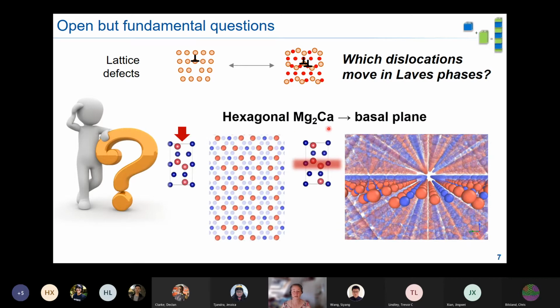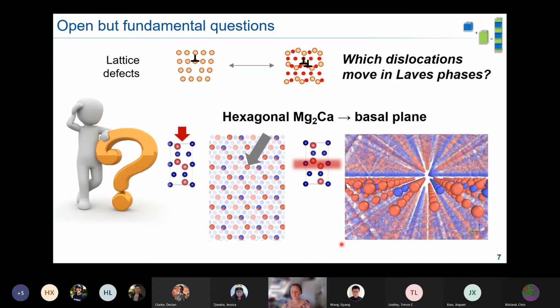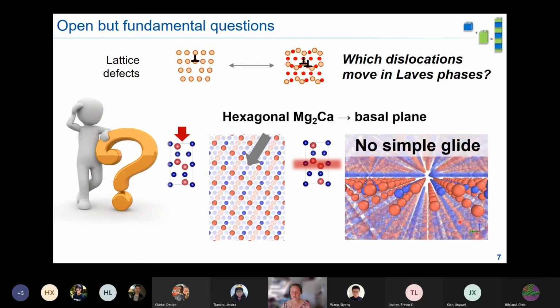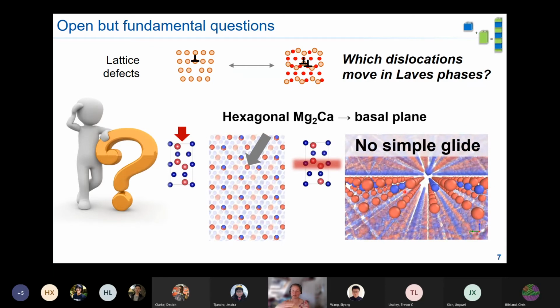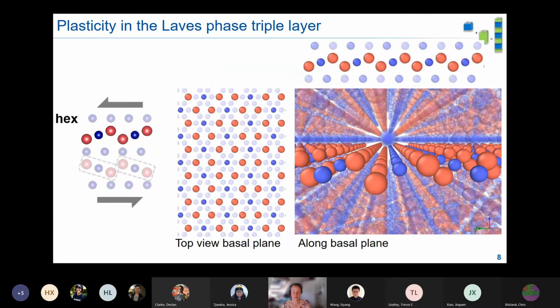There's one example, for example, hexagonal Laves phase, Mg2Ca. And if you look into the basal plane of this, and you can do some atomistic simulations, because for this we actually have potentials, then we can, of course, look along the plane, and we can look from the top, and we then try to shear the crystal lattice. It actually looks all right, right? You think, yeah, you shear like this, and then you get a stacking fault, and that's probably a good candidate for deformation. However, if you look from the side, then you can see that that's probably not going to happen, because essentially the slip plane has to take off and be moved upwards by a long distance.